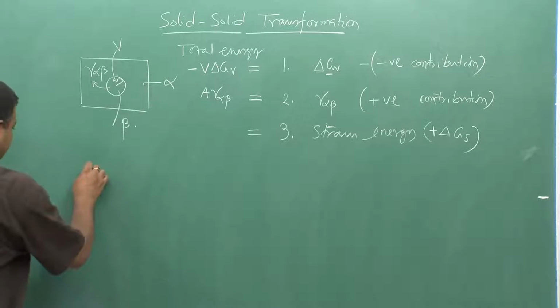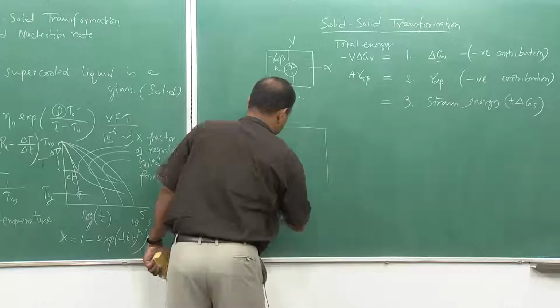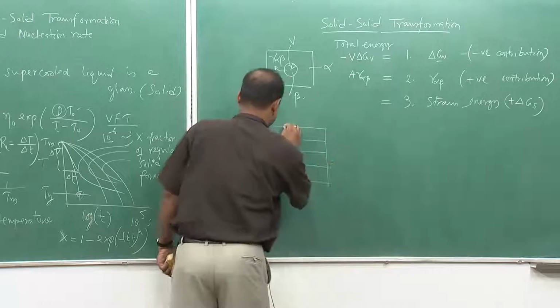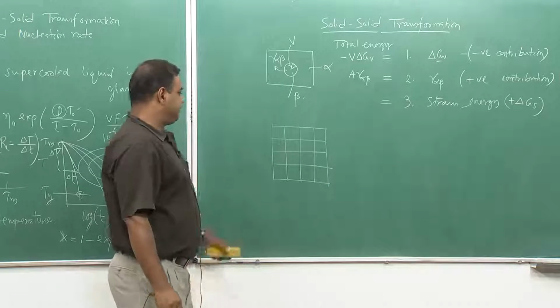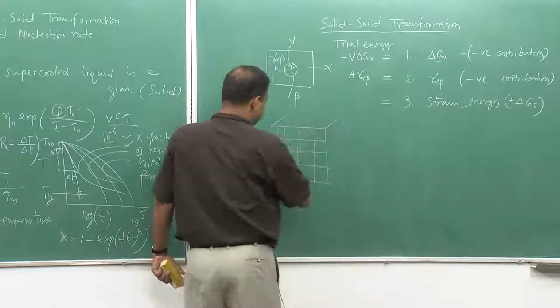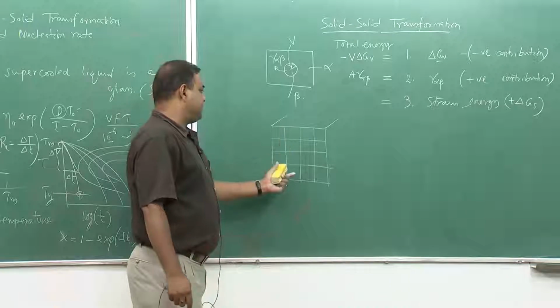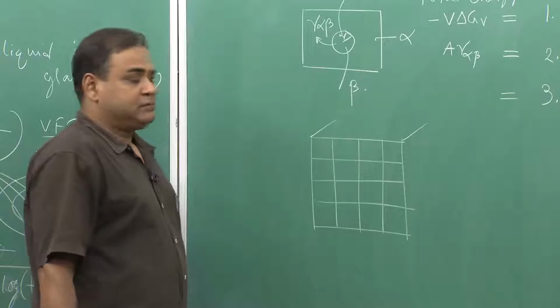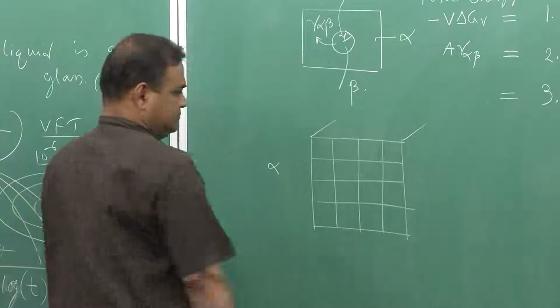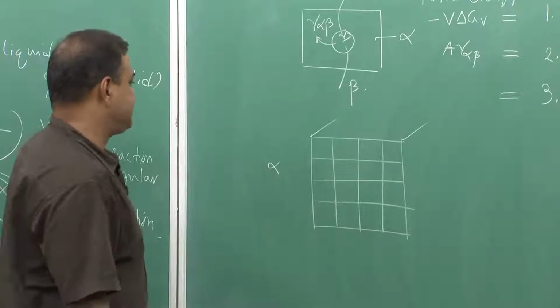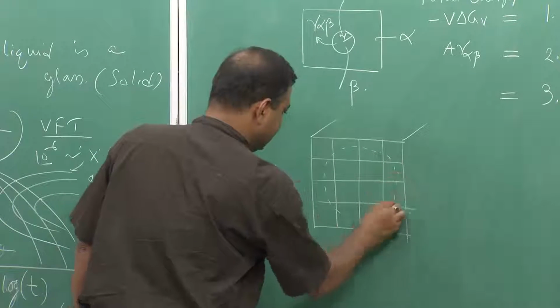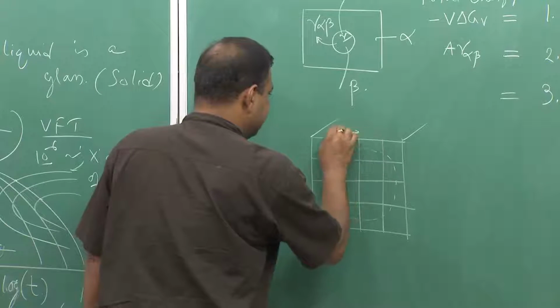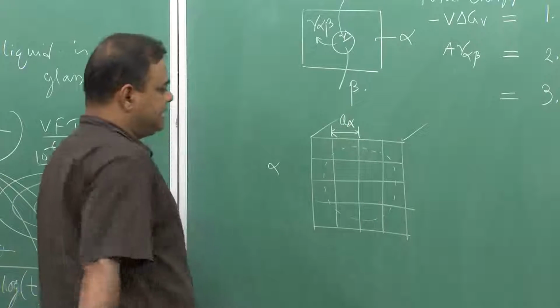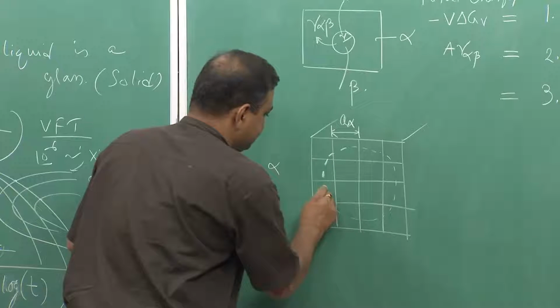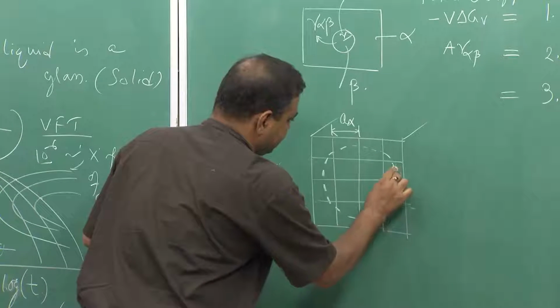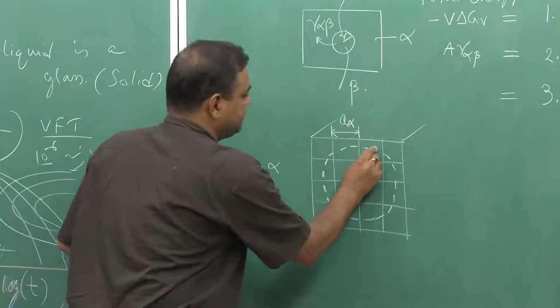Now if I try to see a solid, and we can extend it in 3 dimensions, but let me do only the 2 dimension part. We see that if the solid is a regular crystal, atoms are arranged in a periodic manner. Now if this is the alpha, there could be a second phase which can appear. The second phase can appear like this in this volume, and if this is the alpha lattice parameter, which is A alpha, and this is my second phase, which is beta.